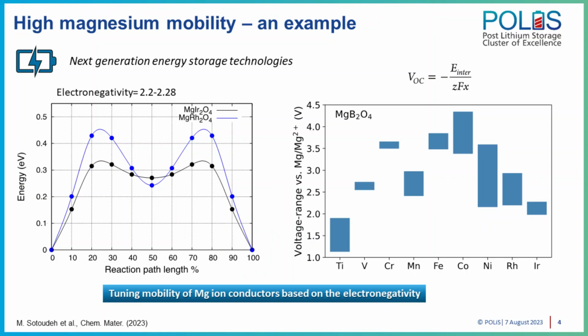We also used theoretical calculations in order to analyze the stability of the compounds. Interestingly, we found that iridium doesn't show any stability in a spinel framework, while rhodium does. And this is something that we proved in a lab: we can synthesize a spinel structure with rhodium, while for iridium we are not able to synthesize that, and it forms different compounds.